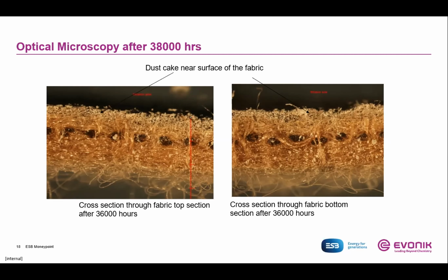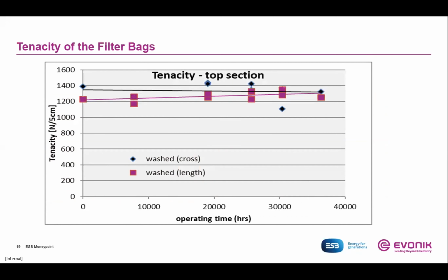And this is a real good indication of a very stable filtration pattern, as well as reduced mechanical wear. Also the tenacity, which is more or less one of the criteria to determine the lifetime of a filter material, is close to the levels of new filter bags. This is due to two reasons mainly. First of all, as mentioned, the operating temperature is quite low, so the chemical aging of the material is not pronounced. Also, the acidic dew points are not a big topic, because then we would normally see some effect on the bags. And the second topic is that the mechanical wear is almost minimized. This is the main merit of this blended felt construction, which does not allow dust to penetrate in and later on, during the pulsing, destroy the filter bags from inside out.